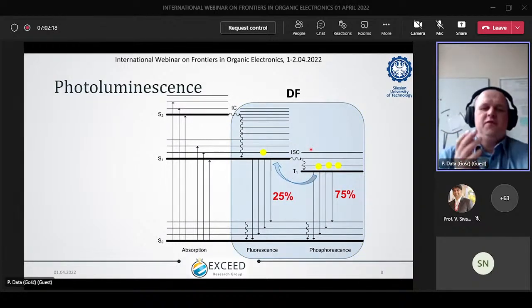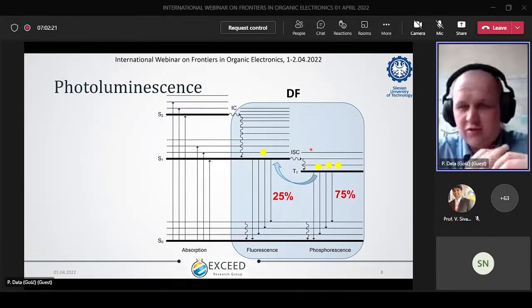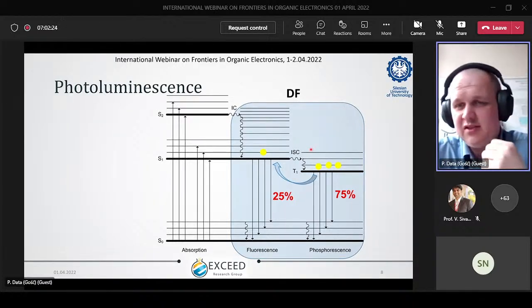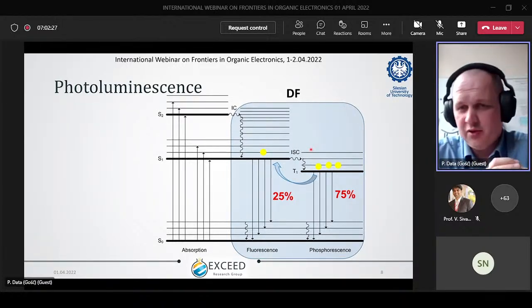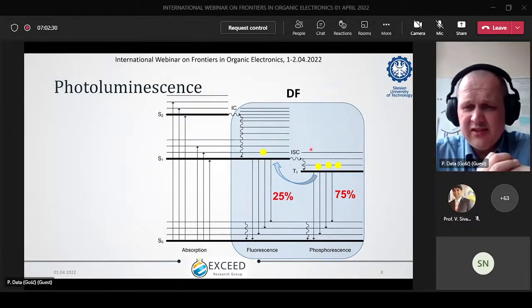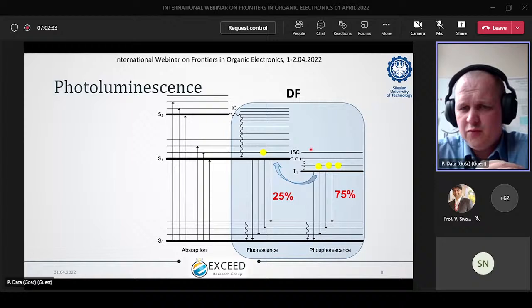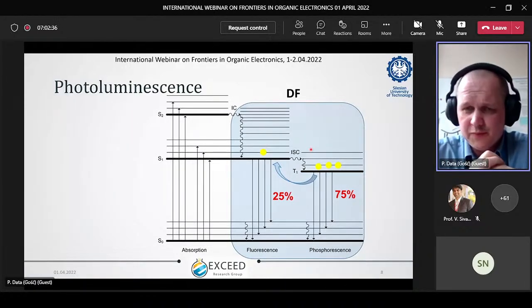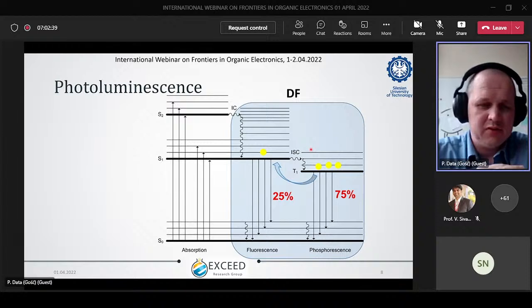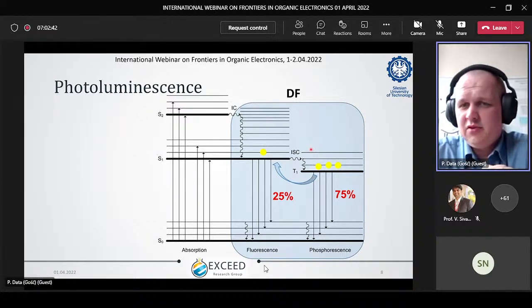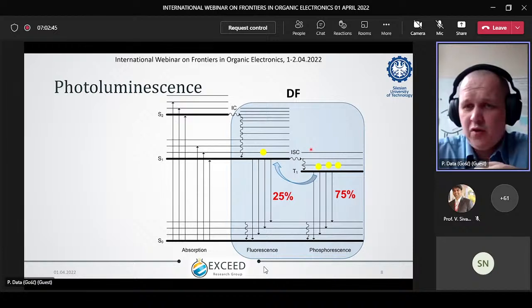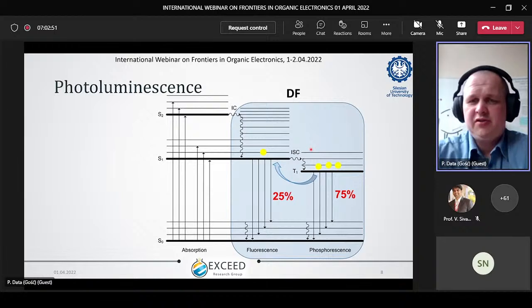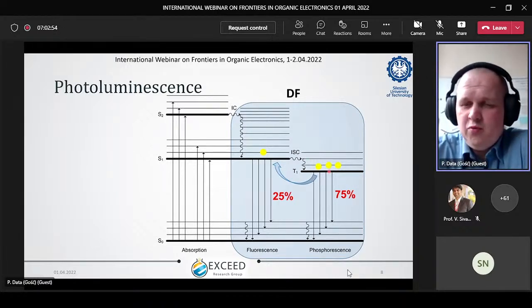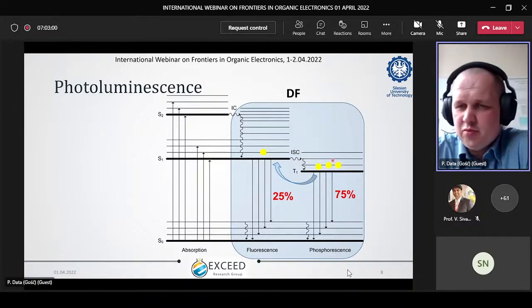Nevertheless, most of the phosphorescence emitters are organometallics, which contain iridium complexes or platinum complexes, and they are quite expensive and not so easy to get. Because of that, scientists started thinking of using another process where only pure organic molecules could be used, or molecules containing no heavy metals. And this process is called delayed fluorescence. And what's the behavior, or what's going on inside? We are going in the completely opposite direction to the phosphorescence emitters or metal complexes, and we are trying to harvest our triplet state. So 75% of the energy is in the form of the excited triplet state.